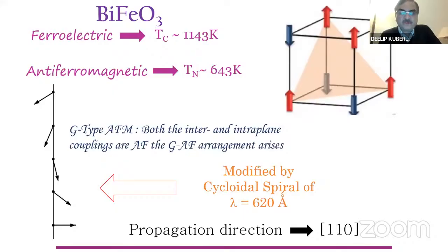because any device which you make, just now we saw the very interesting part which the earlier professor told, that nowadays the ambient temperature should be room temperature, because any device which works at very low temperature is not very applicable for day-to-day life. So therefore these materials have very high transition temperatures, and it has a G-type antiferromagnetism. I will not go into details about what is A-type and all these different types of antiferromagnetism depending upon the in-plane and intra-plane ordering. And it has a modified cycloidal spiral of wavelength 620 angstrom, and the propagation direction is 110. So this is an interesting compound, BiFeO3.